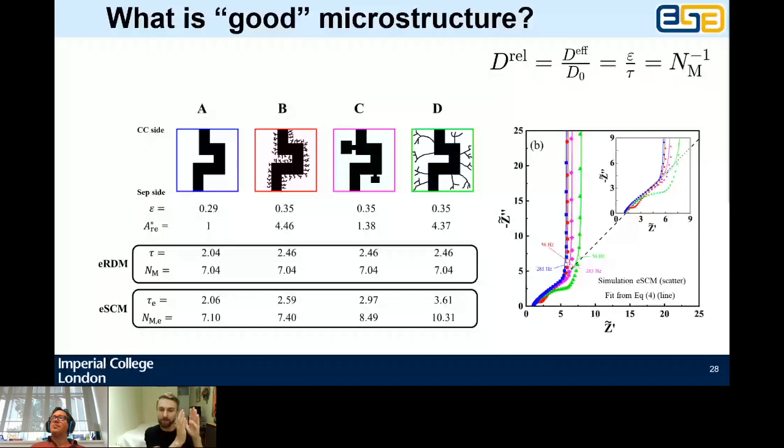So we first remove that, and then we are taking the width of the region from the axis intercept to the asymptote as the metric that we can use. And the equations that justify that are built into the paper, but you're basically comparing it to a conventional, what is effectively finite space Warburg, although actually mathematically it's not, because you're looking at the surfaces. But yeah, all the details are in the paper, it's quite a lot to do by voice.